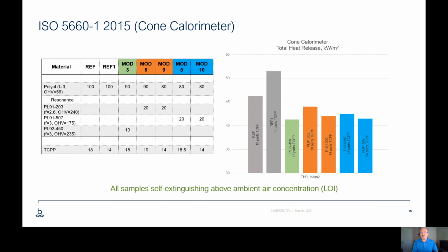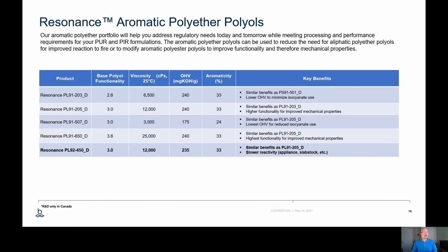Similar to the other material, the PL91-203 and the PL91-205 all seem to improve further with the introduction of our resonance materials. And as a matter of fact, as you can see from the bars that are showing here, starting with the orange bar, when you go from the 18 to the 14 parts of TCPP, we not only did not see a degradation of the total heat release, but we actually seem to see a consistent slight improvement. Not something that I would take to the bank, but certainly a consistent improvement.